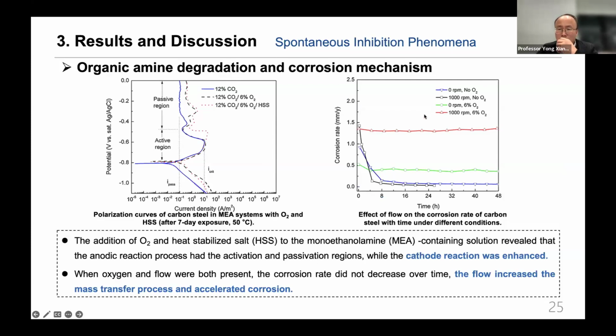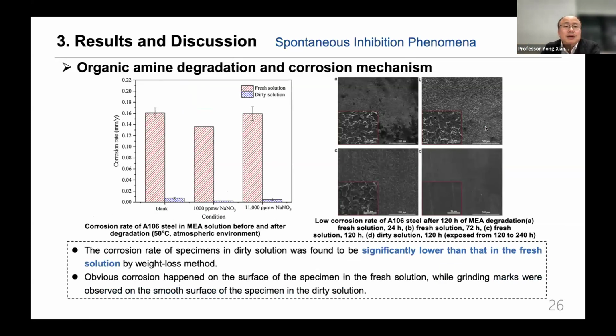This shows that when flow and oxygen are both present in this capture system, you can see the corrosion rate line does not drop. But when there is no oxygen, you can see the corrosion rate decreases with time. What happens in this system? We think that the flow may increase mass transfer and accelerate corrosion, and may also affect the formation of the corrosion products.